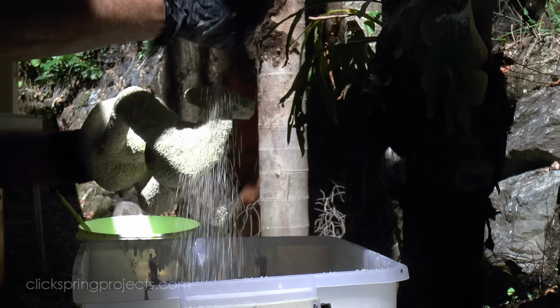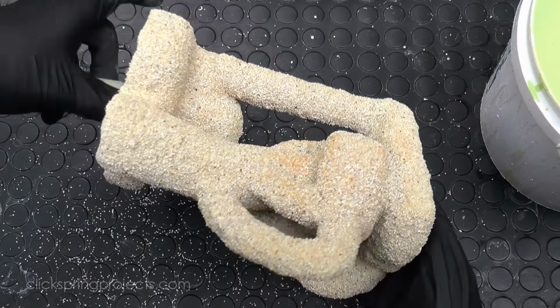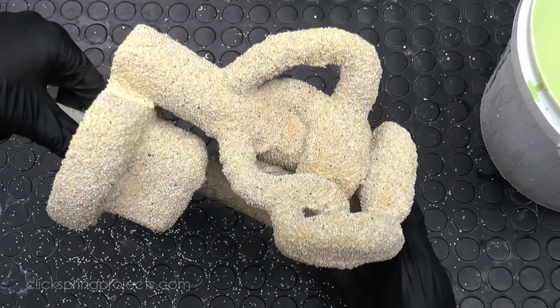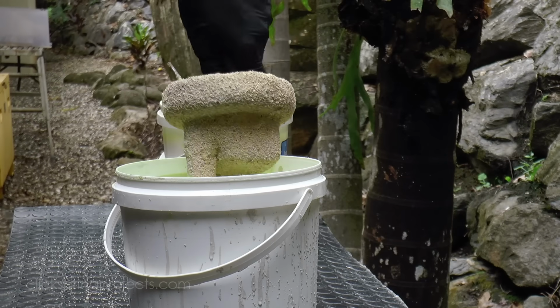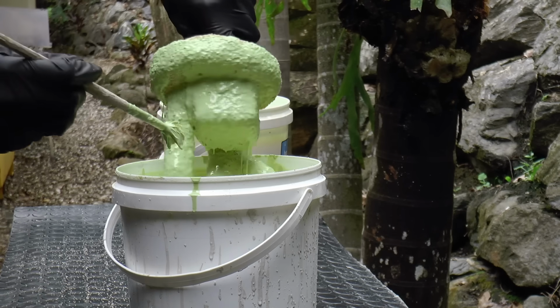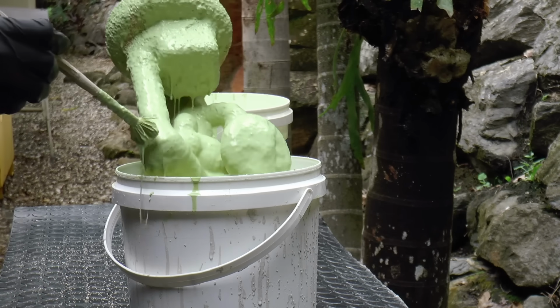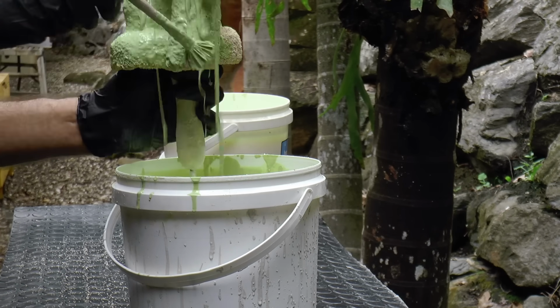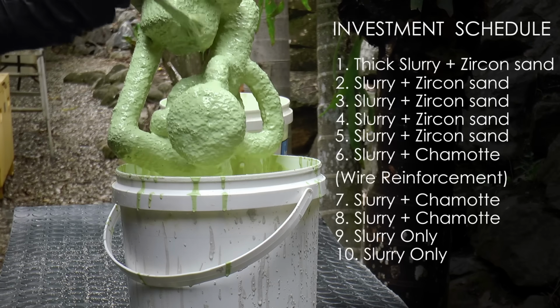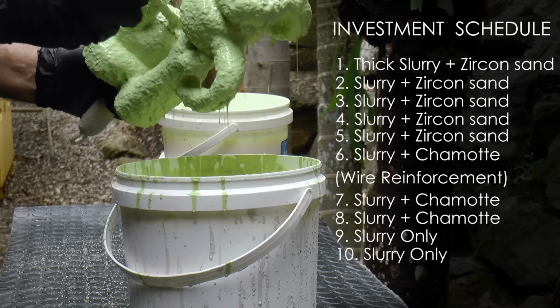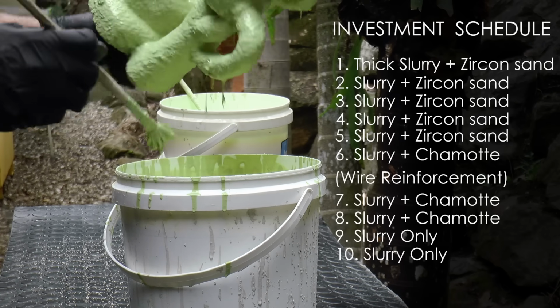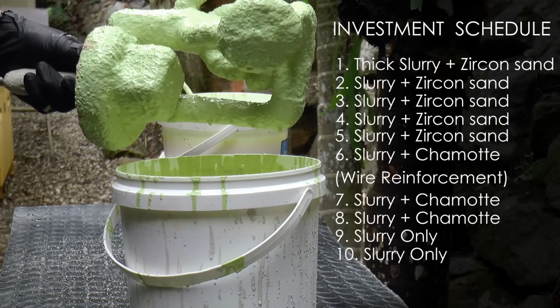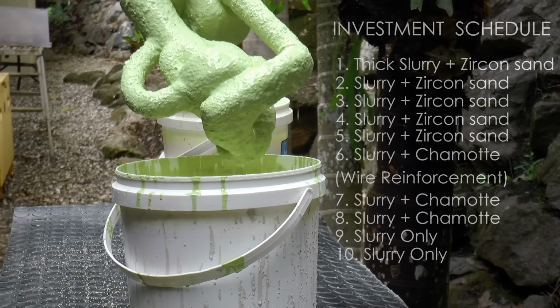Once the final chamot layer is dry, the investment process is completed by adding 2 more layers of slurry only. This gives the mould a tidier surface, keeping the chamot from shedding, and it also serves to make the identification of cracks much easier after firing. The total number of dips will vary a little depending on the nature of the part to be cast, but here's a summary of the investment schedule for this particular mould that I use as a general guideline for all. This schedule will give a mould thickness of between 6 and 10 millimetres.